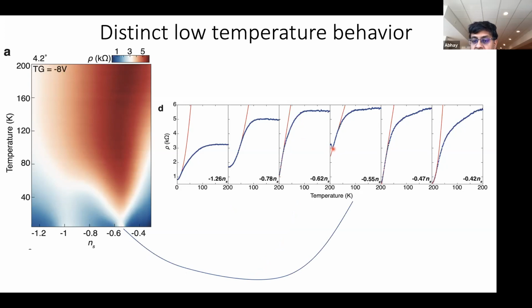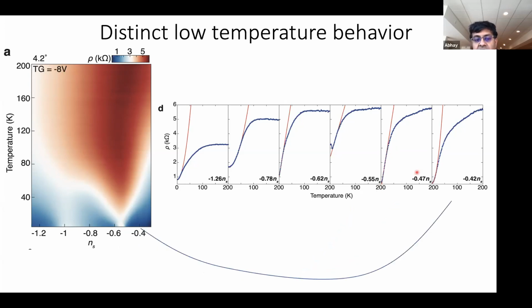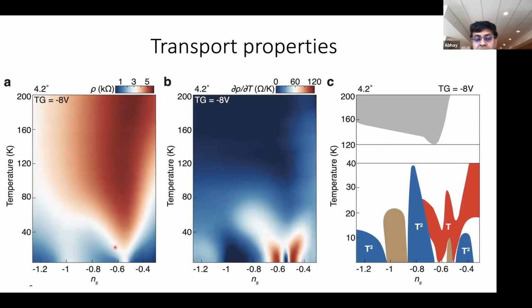Above that metal to insulator transition, as a function of temperature, you see again a region of T-linear behavior, after which it starts to saturate. And if I go to the other side of doping, to the metal insulator transition on this side, once again I see a particular point where R versus T looks linear in T all the way down to low temperature. And if I go even further, I'll see once again T² behavior emerge. So just on the basis of resistance as a function of temperature, we can break this temperature density phase diagram into the following behavior.